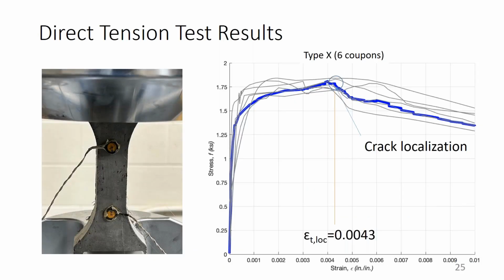For this batch of tests, the localization strain, remember that is the delineation between strain hardening and strain softening, was 0.43%. And just so you can compare, steel yields at 0.2%, right? So you can see that the material will continue to remain in the strain hardening range, even well beyond steel yielding. So again, this is an important design parameter to keep in mind as we go forward. These tests are conducted by making a coupon and basically ripping it apart in the machine, as shown on the left.